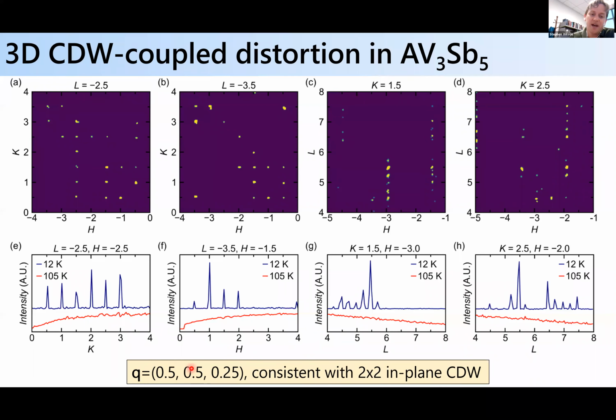So basically, it's a half-half wave vector in the AB plane, which is consistent with this 2x2 order that the STM people see. But then there's an interplane periodicity as well. So it's basically a half-half-quarter for the cesium system. And I'll just mention here that this is the data for the cesium vanadium-3 antimony-5, but for the potassium